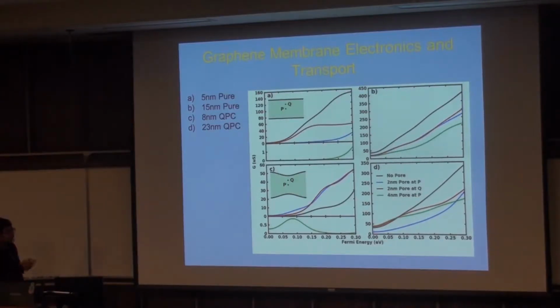So the idea is, as the DNA is being pulled through, the conductance or current will be changed. This is important because if we can tune the graphene layer to be in a regime where it is highly sensitive to changes in the Fermi level, perhaps then we can see large changes in conductance as the DNA molecule is being translocated.